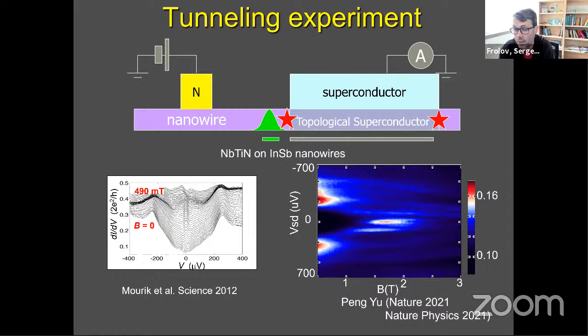So that's an advantage. Long mean free path is good because that's one of the unspoken critical properties for all Majorana systems, because you're trying to create P-wave superconductivity, and disorder of any kind, magnetic or not, suppresses P-wave superconductivity. There is no theorem that protects superconductivity from disorder for P-wave. And finally, the last property that's good is easy contact to metals. So when we put down a superconductor, this creates a possibility to transfer electrons between superconductor and semiconductor without a Schottky barrier or something like this. So you can actually induce strong superconductivity in a semiconductor. Even some theorists say it's too strong. We have to dial it back a little bit. Right? But if we had a Schottky barrier, it would just be a non-starter. So then between, let's say, indium antimonide and indium arsenide, those are pretty similar.